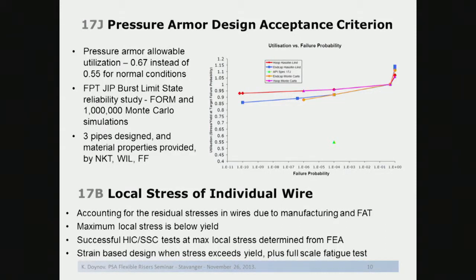And then I also already mentioned that the HIC and SSC test should be done at the maximum local stresses plus having the residual stresses introduced into the wire specimen. And that's for those rare cases where the stress exceeds the yield, then we're introducing a strain-based design to account for that, which is going to be followed by choosing some of the load cases for the full-scale fatigue test to include that type of loading.